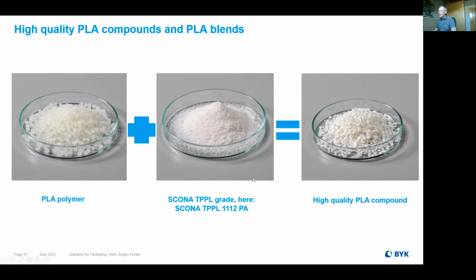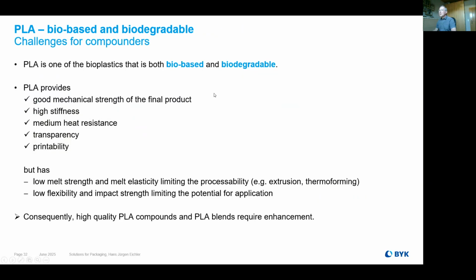It's more or less a powder which we are producing out of these modifiers, and coming now to the point what it's still doing in a PLA. As I said, the PLA is still bio-based and biodegradable. It has good mechanical strength and for the final good, high stiffness and medium heat resistance. It is transparent, printability, but the major weakness for this material, it has a low melt strength and melt elasticity.